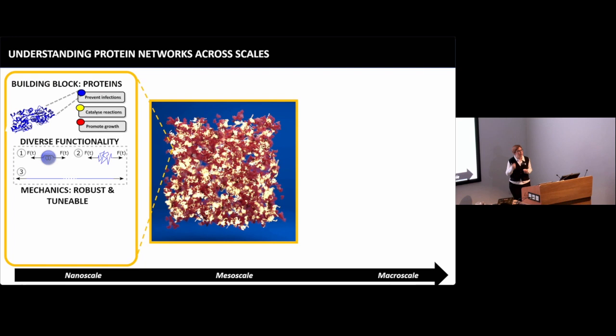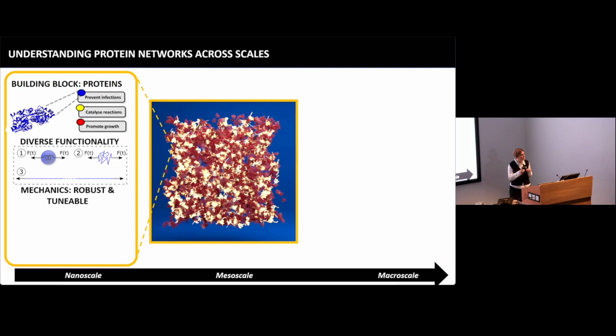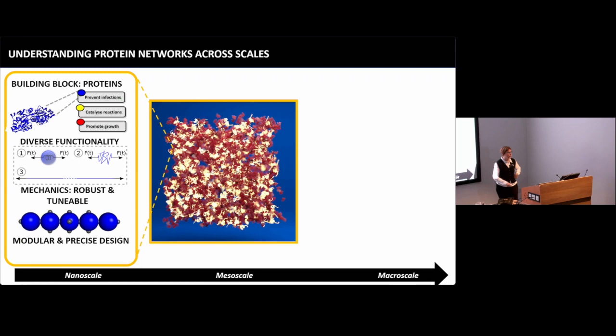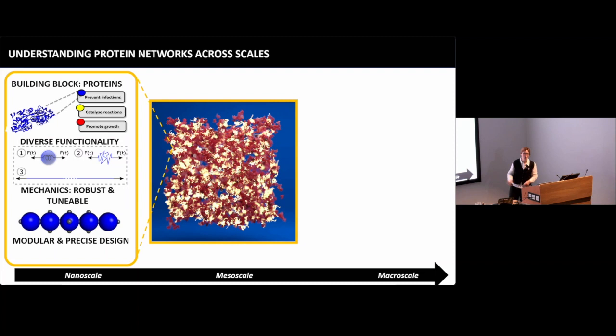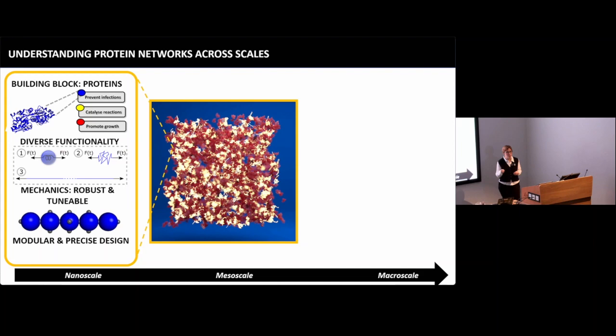So we can do manipulation of the protein. We can do site-specific exchanges of amino acids to tune that mechanical response. And we can also use protein engineering to dial in more modular design to these systems. So in this little cartoon here, you can see a polyprotein. You can engineer this polyprotein to be a specific protein type, to be connected by a certain linker length, and you can even engineer the way in which this protein will connect with other proteins in the system through chemical cross-linking.